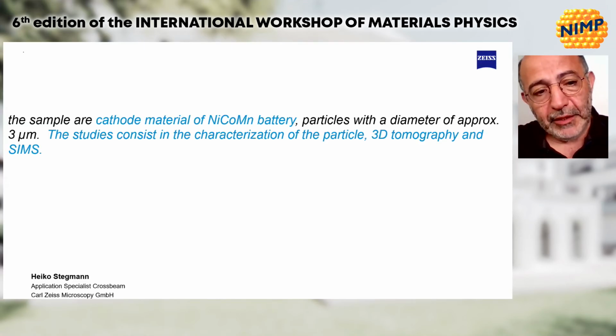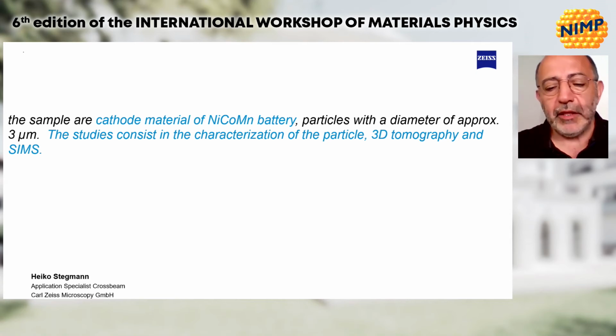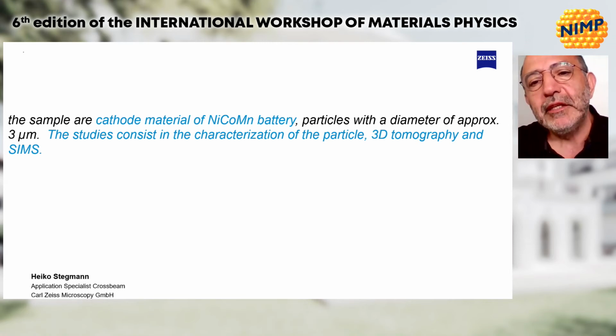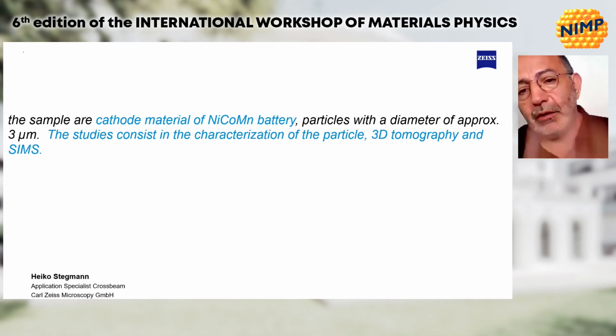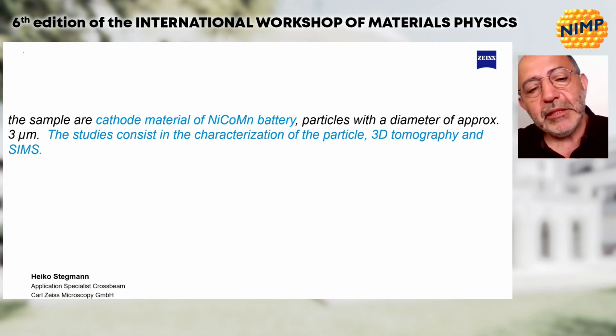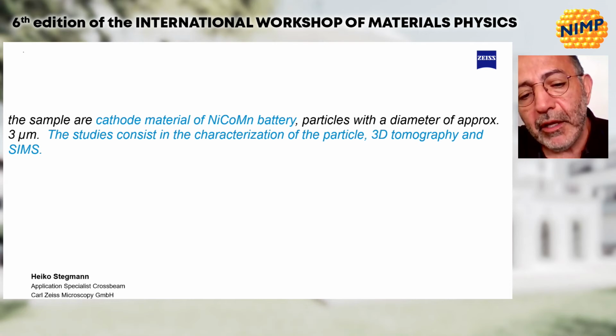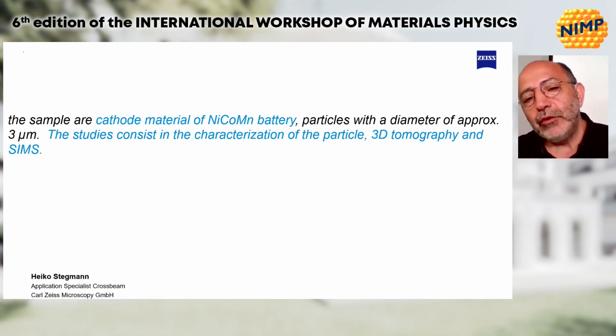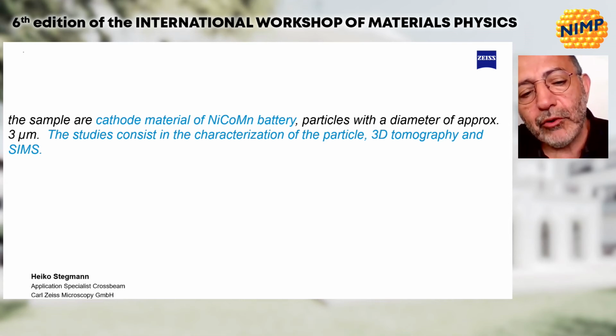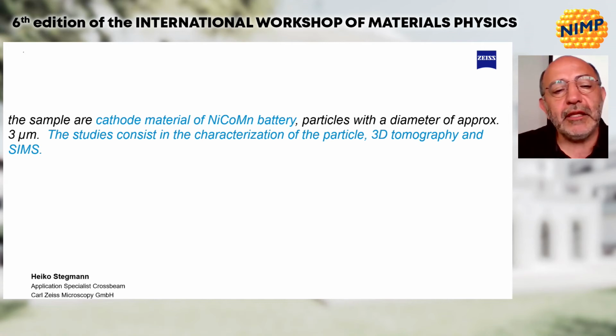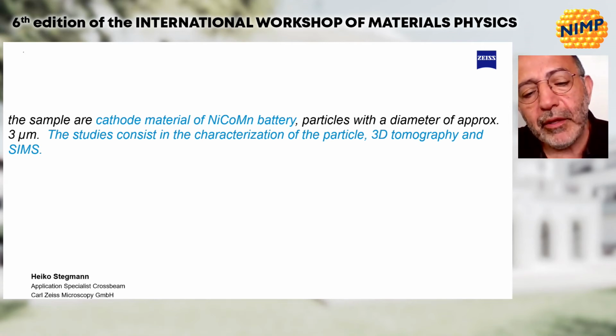The target of the study was to investigate, in a huge context, the particle change given by the cycling of batteries, just to see what is happening inside the battery after many cycles of charge and discharge. What we did is very similar to the example shown before. We took the big sample with X-ray tomography to select the area of interest, then moved to the FIB system with a laser correlated cut system, and then moved again in the same tool to finally make the final polish with the gallium FIB and correlate this lateral high resolution image with a mass spectrometry analysis.